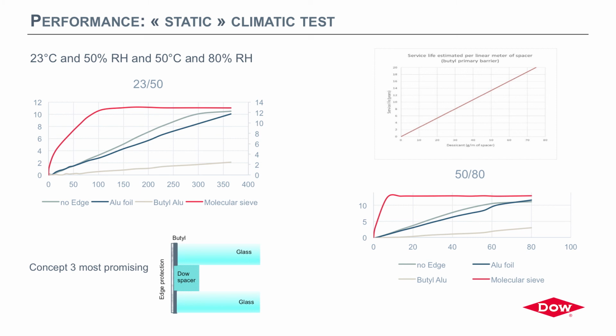When we look at higher temperature and humidity, all the diffusion process is accelerated, of course, and so we see that the full capacity is reached after less than 100 days, but still performing for our concept. So based on that, we are extrapolating a bit what the lifetime expectancy could be, but of course, this is not the official 1279 test. This is not a cycle test, so this is what's next.